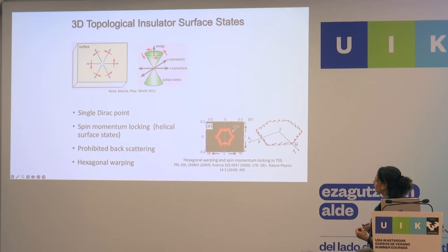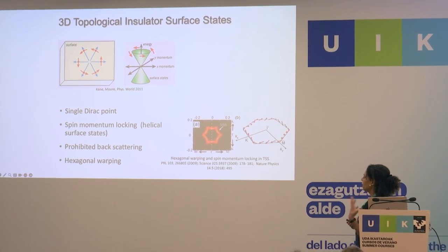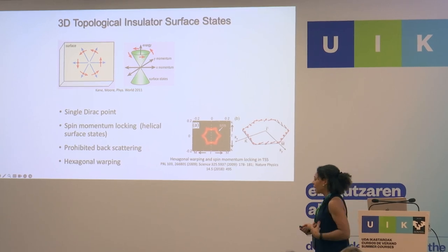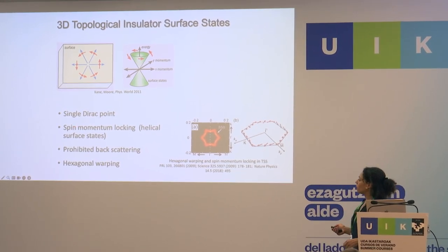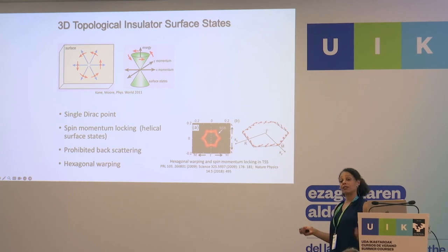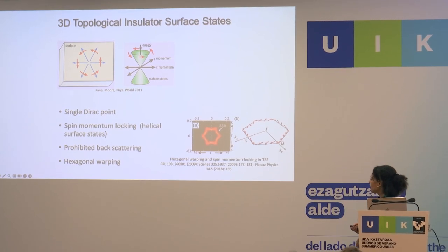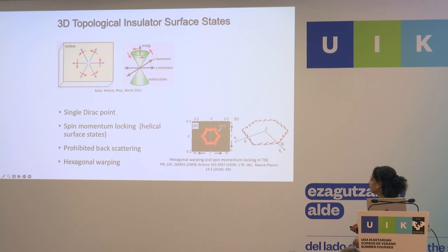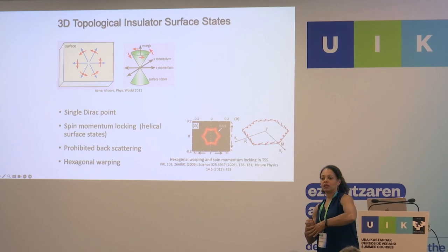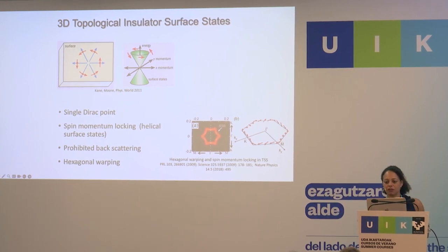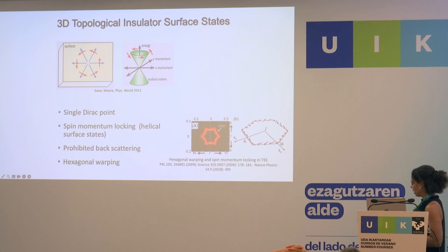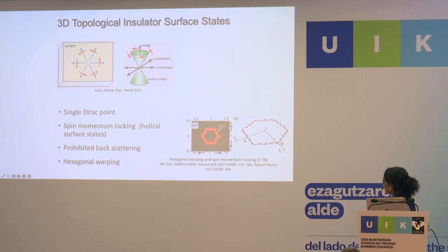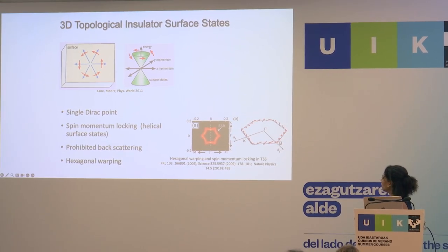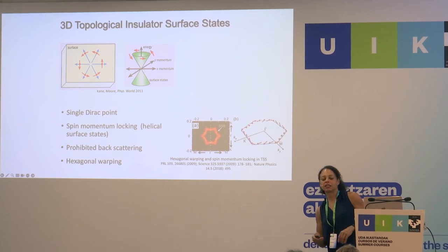I mentioned some of the interesting properties yesterday, but explicitly for magnetic properties, what's interesting here is that these surface states not only have less backscattering and other properties, but they also have spin momentum locking, which gives opportunity for separating out spins in these cases. And they have hexagonal warping, which affects their spin structure. And this is just due to the trigonal nature of the bismuth selenide structure, threefold symmetry of bismuth selenide. And I'll show that this hexagonal warping leads to an out of plane spin component in bismuth selenide, which is also useful when coupling to different sorts of magnetic materials.